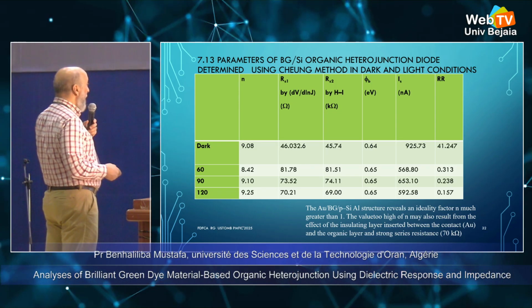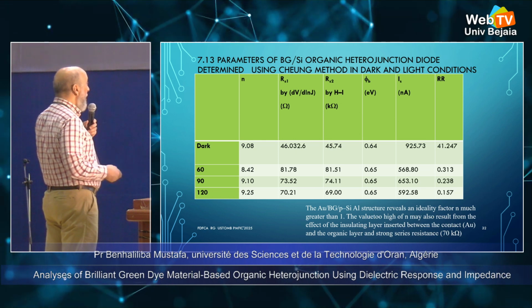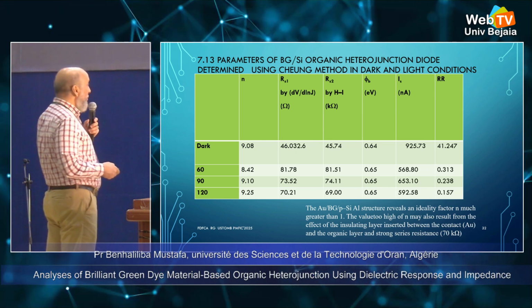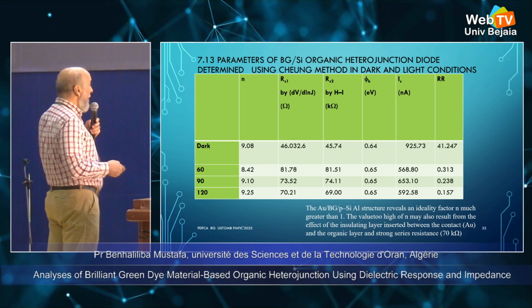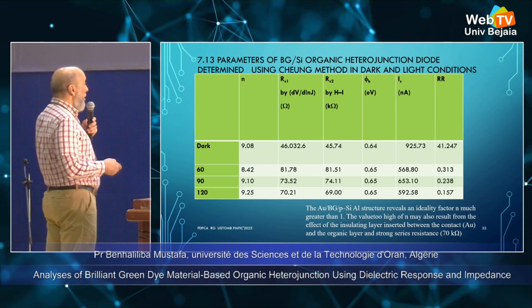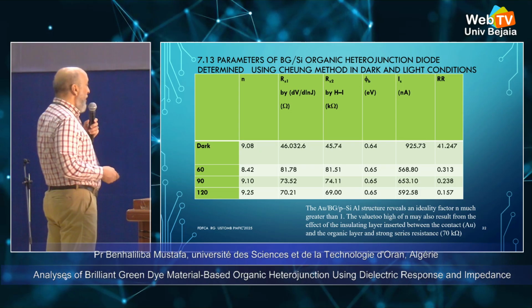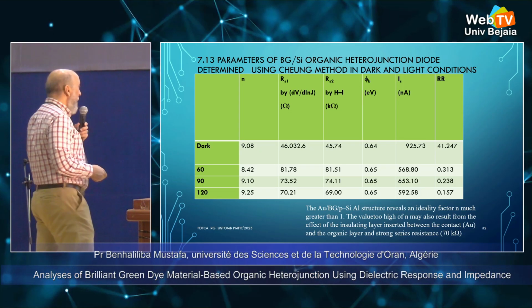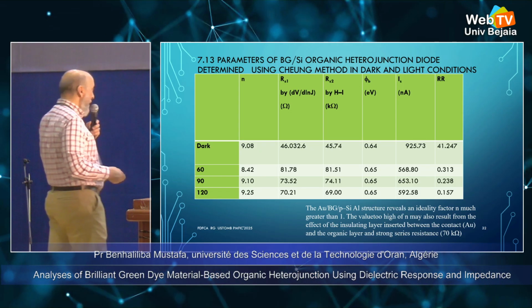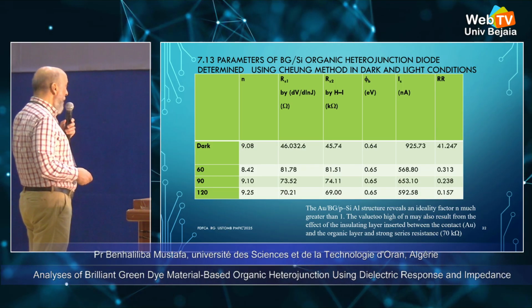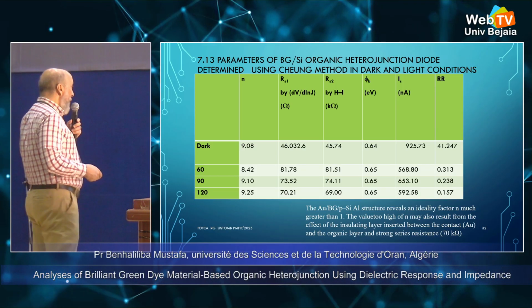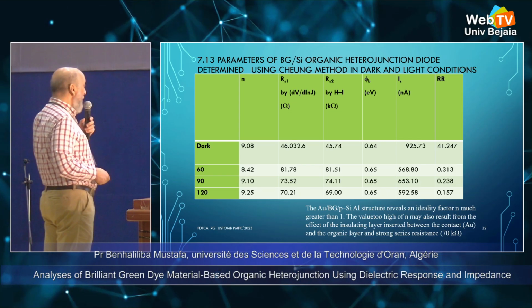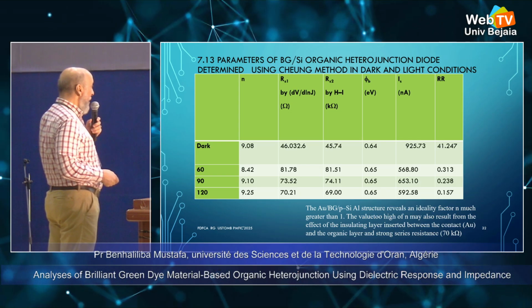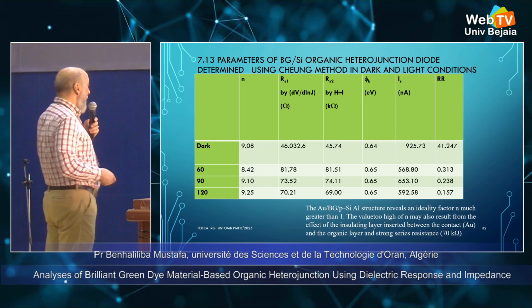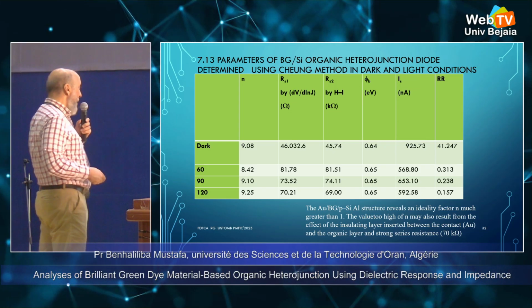Phi_b in electronvolt, we have these values. Saturation current in nanoampere and rectification ratio have these values. So our structure reveals an ideality factor n much greater than 1. The too high value of n may also result from the effect of an insulating layer inserted between the contact and the organic layer, and strong series resistance.